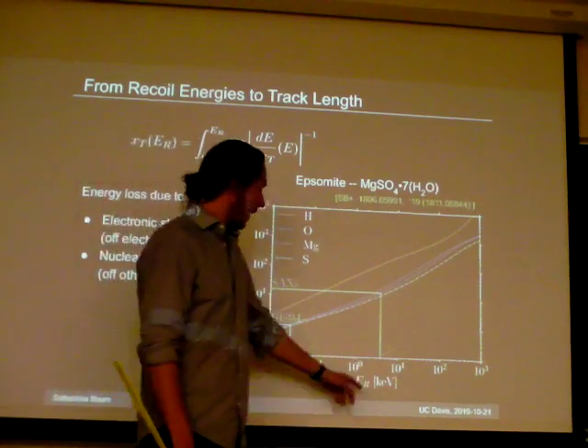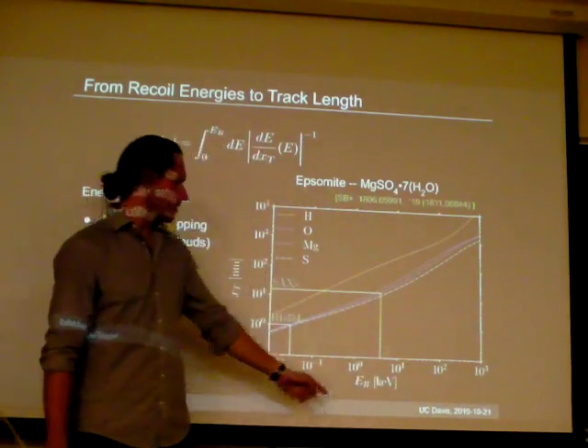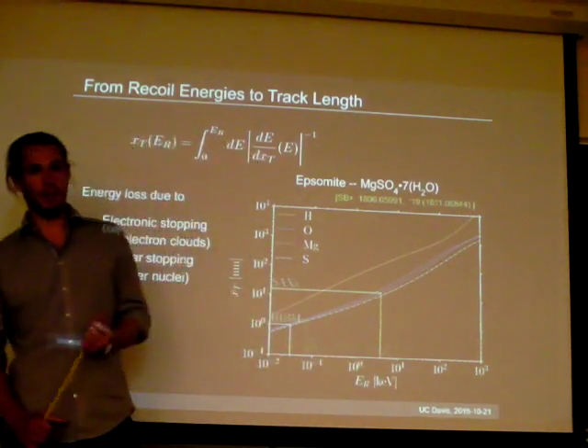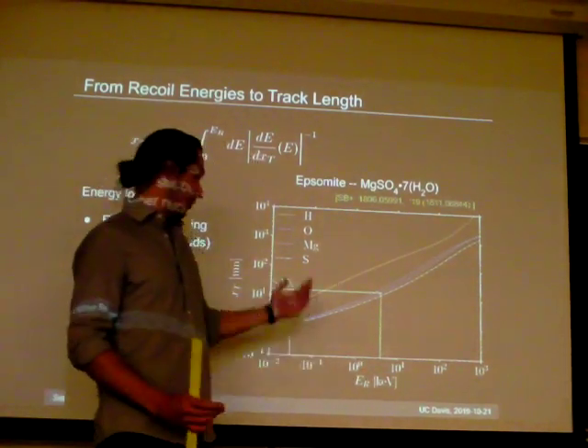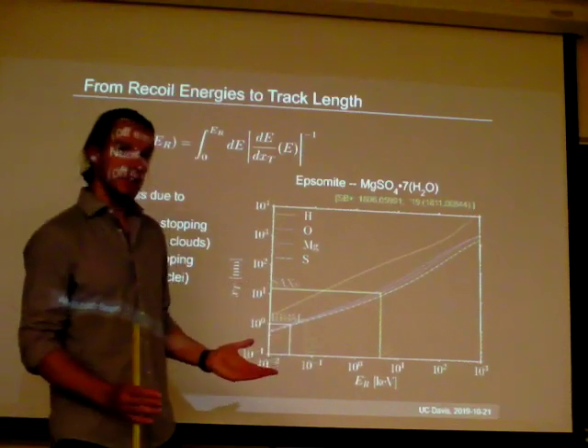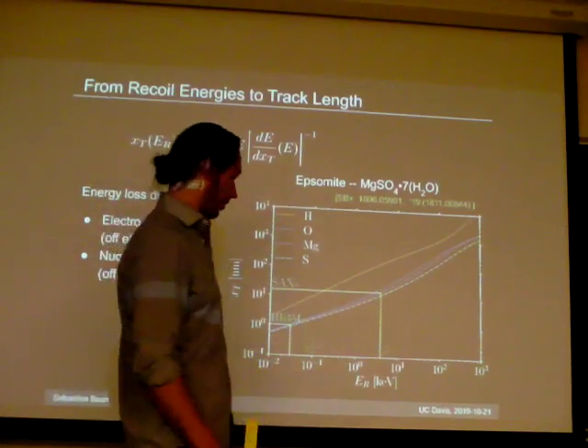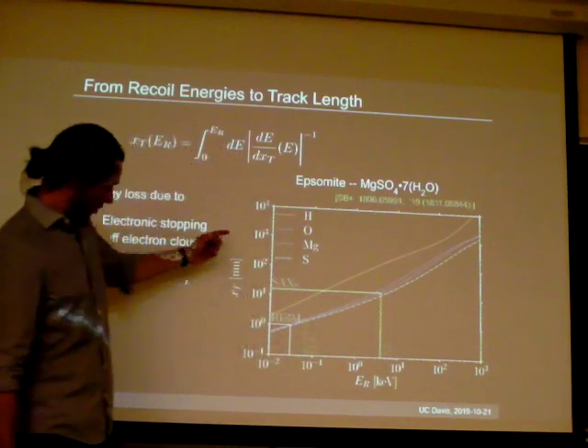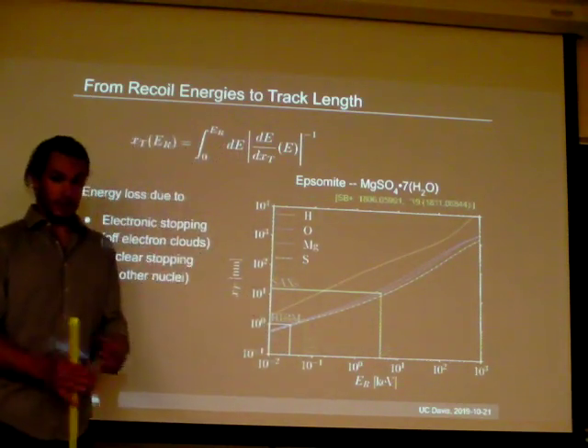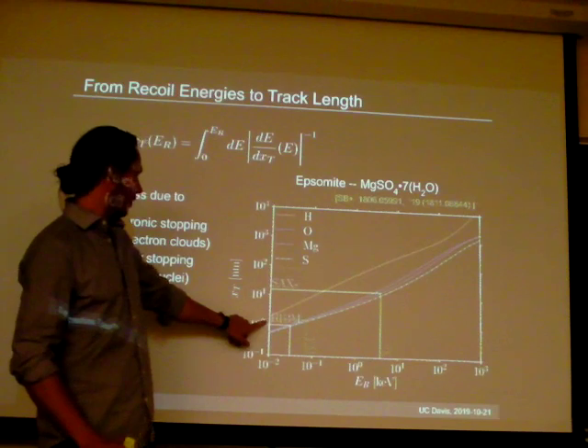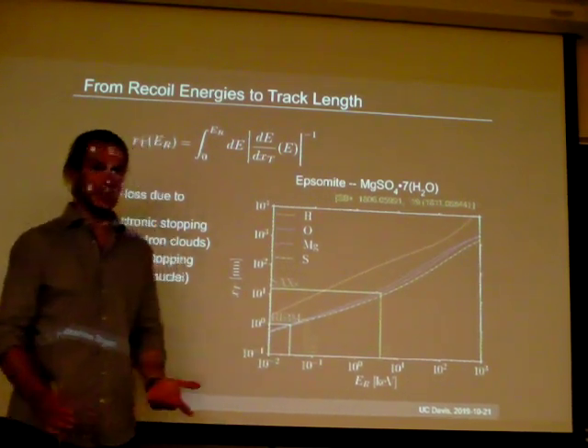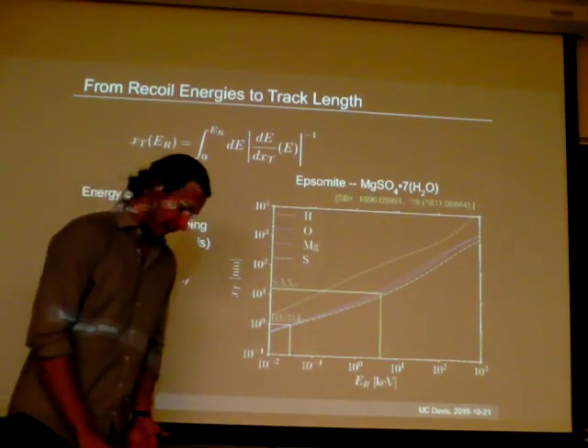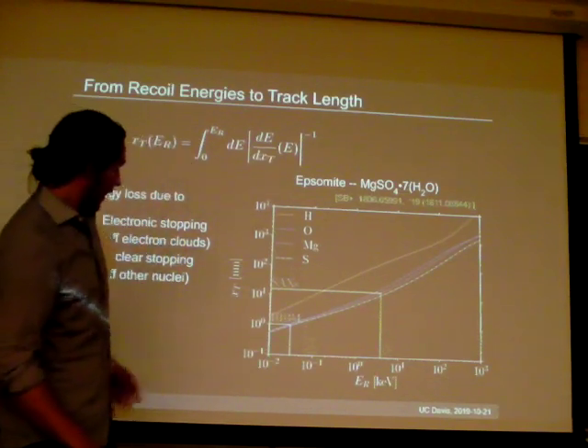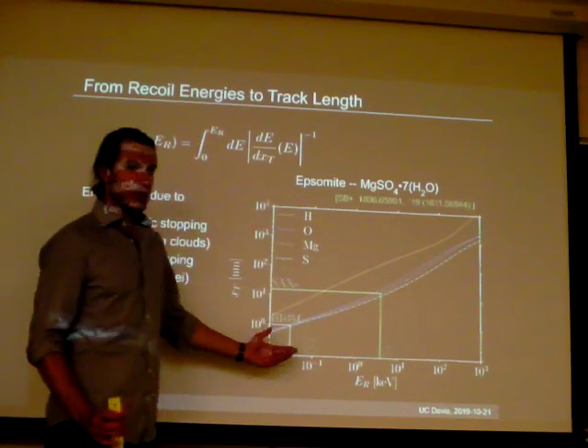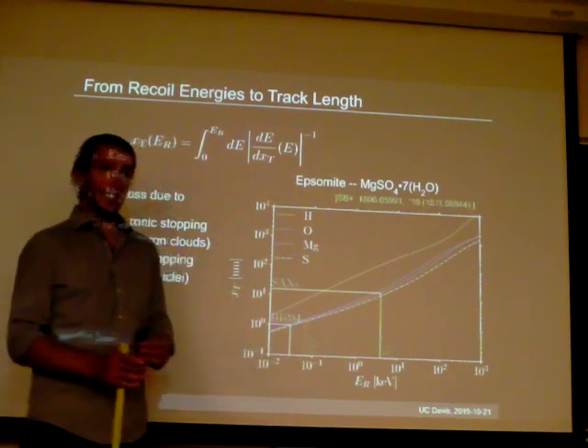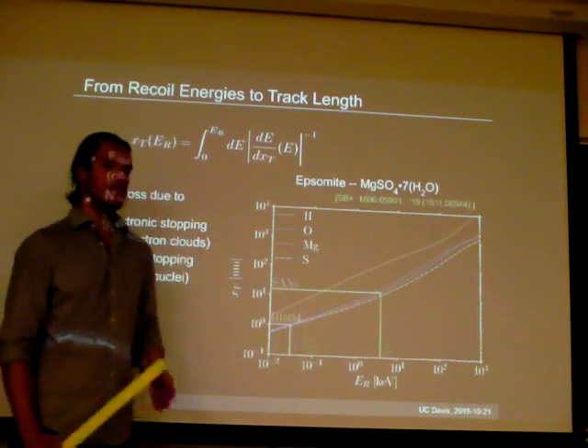And that is a recoil threshold that's comparable to what you can do in a liquid xenon type experiment, right? So if you're able to do this, you have the same energy resolution and threshold as xenon experiments have. Now, imagine you have a much higher spatial resolution readout. The example we put on here is helium ion beam microscopy, which is a fancy version of general ion beam microscopy. And this has spatial resolutions on a nanometer scale. It's actually been demonstrated to have sub-nanometer spatial resolution.